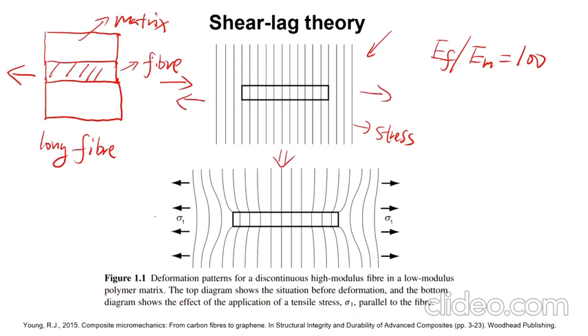In reality, when you load it, this line here is the stress distribution. What happens is the stress is distorted — it's not uniform anymore. It starts quite uniform but changes when getting close to the fiber. This stress field is quite distorted along the fiber. This induces shear stress because there is a mismatch between the fiber and matrix, so shear stress develops between the matrix and fiber.